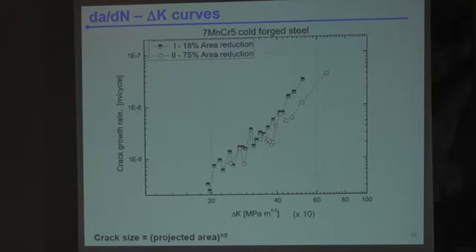In terms of crack propagation rate in the Paris formalism, what does it give us? So you have two things to decide: how you are going to measure your crack size, because of course you have plenty of points. So this here is the square root of the projected area, but you could do it differently. You could use the depth or the surface length, but they basically all give the same result. And the delta K is obtained from the Murakami formula, based again on the projected area.